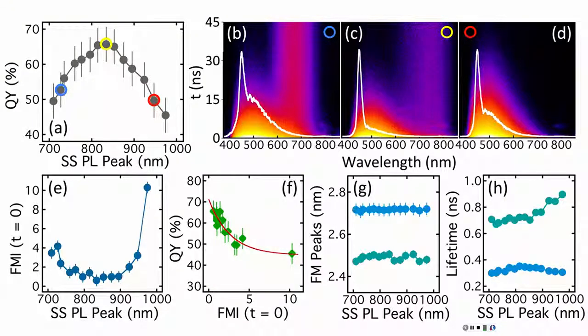So you think it's influenced by quantum confinement. Yeah. We think these are the direct. This is very fast PL, like I said, sub-nanosecond. You can kind of see two peaks. If you look at the shoulder, I'm not quite sure what to make of the shoulder. But what we're trying to understand is that the strength of this fast, direct decay anti-correlates with quantum yield.